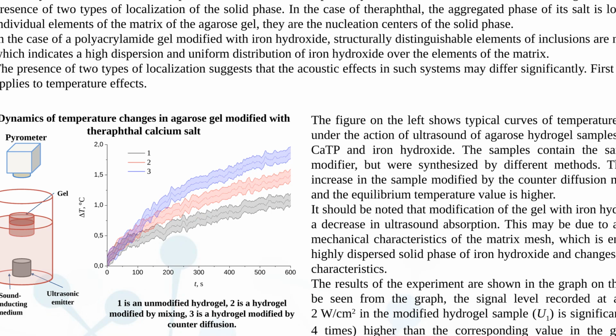The temperature curves shown here demonstrate the dynamics of temperature increase during ultrasound exposure of agarose hydrogels, modified with calcium substituted theraphthol and iron hydroxide. The samples contained the same amount of modifier, but were synthesized using different methods. The sample modified by counter-diffusion showed a faster temperature increase, as well as a higher equilibrium temperature.